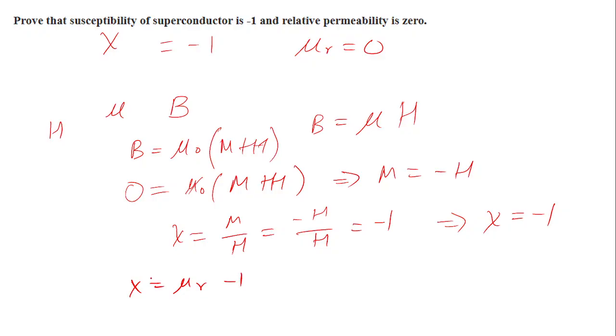So we have shown that for a perfect superconductor, susceptibility is -1. The relation between susceptibility and permeability is this. Now susceptibility is -1, which means -1 is equal to mu r minus 1. That means mu r is equal to 0. That means for a perfect superconductor, susceptibility is -1 and relative permeability is 0. That we have shown.